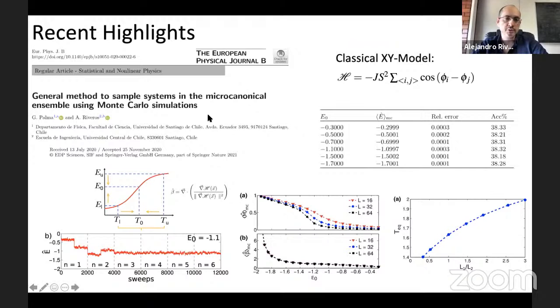And the last work that we want to show corresponds to the other line of Monte Carlo simulation. In this work, we obtain a general method to sample microscopic configurations compatible with a fixed energy E0. This method relies on the existence of an estimator of temperature and an equation of state. So by iterative simulation, we can find the temperature T0 compatible with E0, which agrees with the energy input, and the method has a great accuracy as shown by the values in this table.